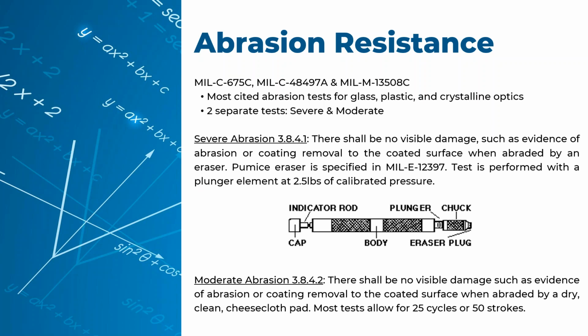Severe abrasion is a very similar test with the strokes, but you actually have a calibrated pencil or pen-like device where you have 2.5 pounds of pressure and a rubber pumice eraser, and you pass this over the coated surface multiple times, and then again you perform a visual check for any induced stress on your film.